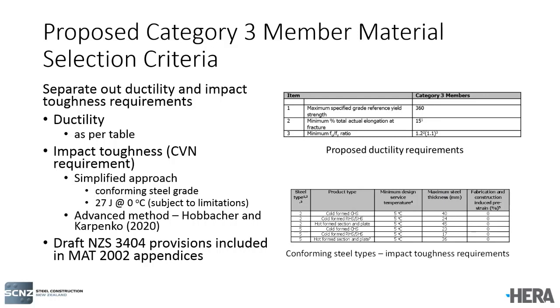The second approach in terms of impact toughness or Charpy V-notch impact energy requirements is that if you are outside those limitations of the simplified approach, you might have a material that's too thick, or the design service temperature is too low, then there's a requirement to use an advanced method by Hobbacher and Karpenko. Dr. Karpenko from the HERA Welding Centre will talk about this new method later in the presentation.